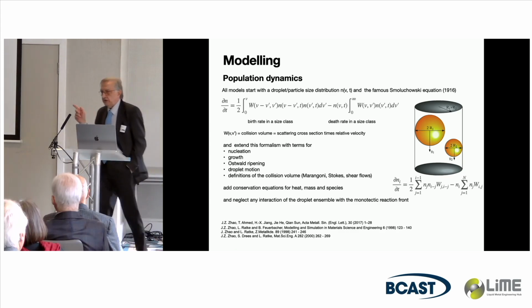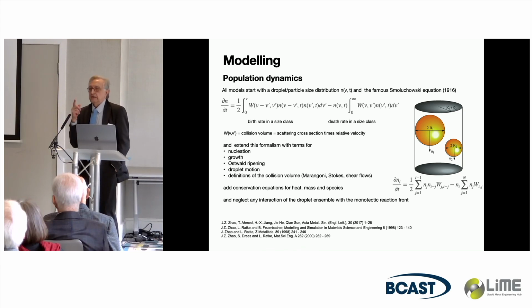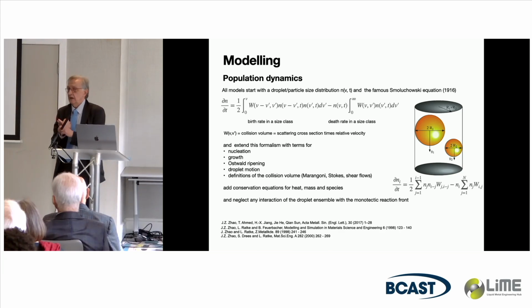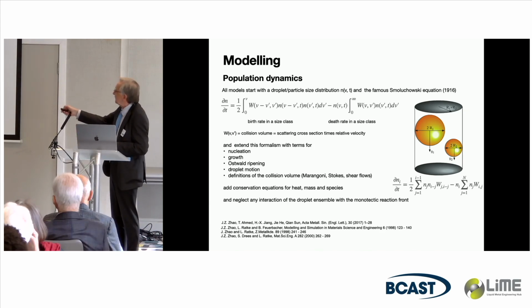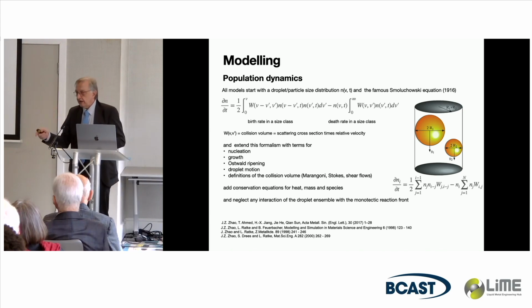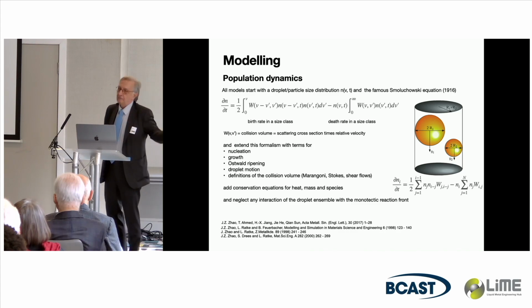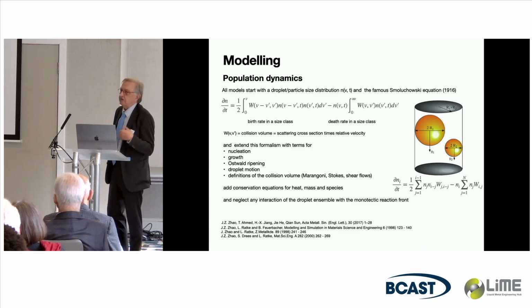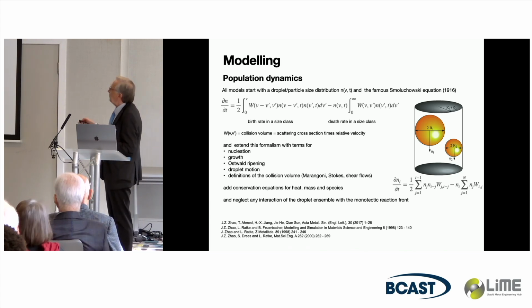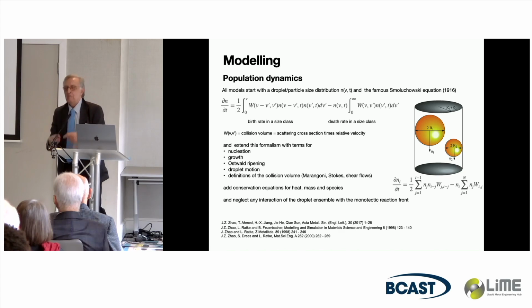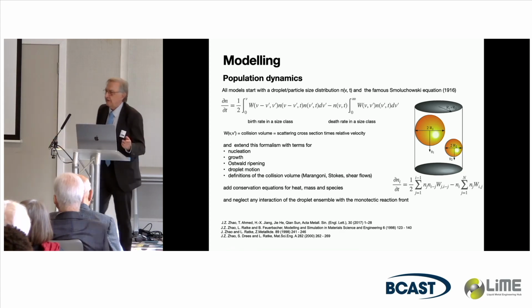Well, this is the first link, because if you think about this, in the 80s and 90s, one of the hypes that came up was fractal structures, diffusion-limited aggregation, diffusion-limited cluster aggregation, reaction-limited cluster aggregation, and the mean field theory for that is exactly this equation. And cluster aggregation is exactly one of the models to describe the formation of aerogel structures. So when I, years later, came into the business of aerogels, I thought, beautiful, what a luck. You can use the same mathematics as you did for immiscible alloys, by accident.